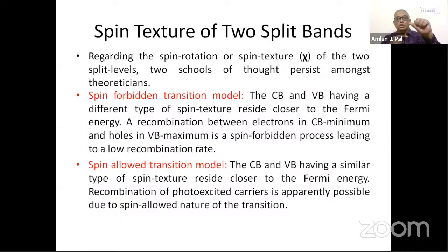So there is a quantum model which says that it is a spin forbidden transition model. That is, the conduction band and the valence band have different types of spin texture. They reside closer to the Fermi energy. Hence, a recombination between the electron in the conduction band minima and the holes in the valence band maxima is a spin forbidden process. So since it is a spin forbidden process, we get low recombination loss. So that is the first model, what is called spin.